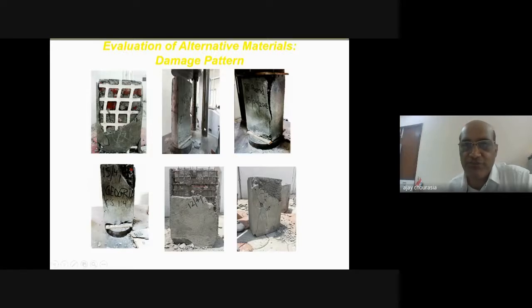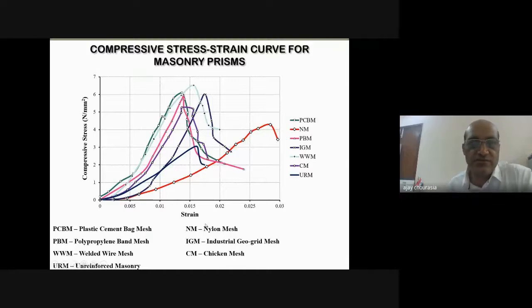This is the damage pattern obtained on the prisms jacketed using different options, and the results were then plotted in terms of compressive stress and strain, which shows that the plastic cement perforated bags have shown a phenomenally good enhancement in compressive strength, to the tune of around 6.2 MPa, whereas the maximum was achieved in the case of GI welded wire mesh, around 6.4 MPa. Whereas in the unreinforced masonry, the strength was around 3.2 MPa.